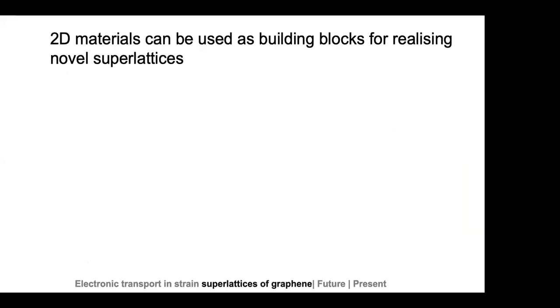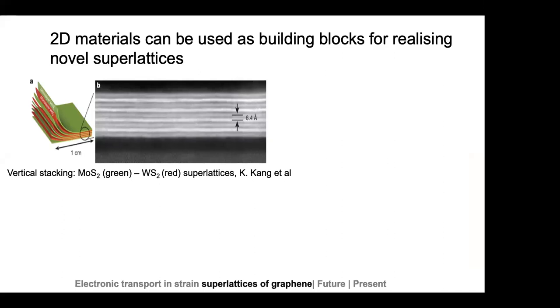So two-dimensional materials, as many of you might have heard of them, they're quite in right now, have functional properties which are quite different from the bulk material. And using two-dimensional materials as the building blocks, it is possible to develop new superlattices which will have the properties custom made according to your needs. So some of the techniques which are used for generating such superlattices, one of them is vertical stacking. For example, you can have single layers of molybdenum disulfide and tungsten disulfide, both of them semiconductors, piled up on each other. And there's a superlattice which has been seen to have optoelectronic properties quite different from either of those two 2D materials.